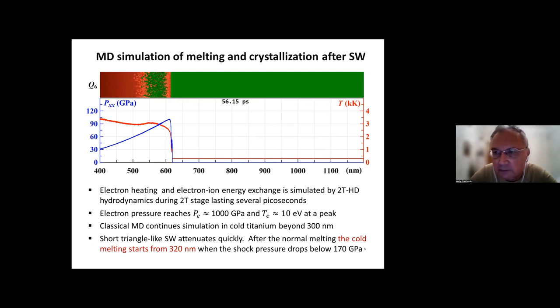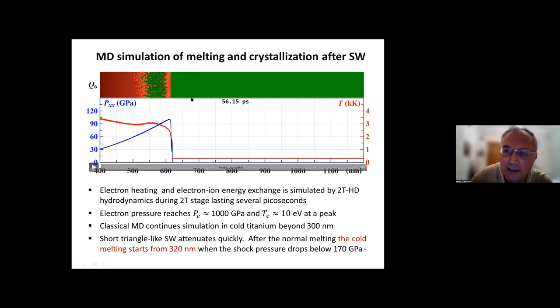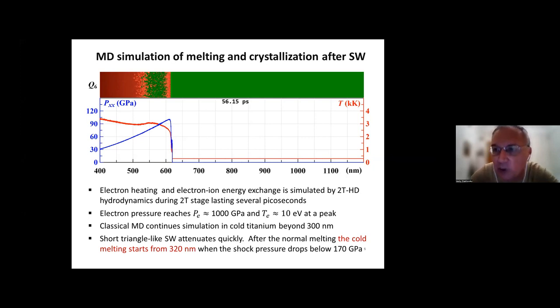Since you mentioned that the shear stress is very important, this actually looks more like Richtmyer-Meshkov instability rather than Rayleigh-Taylor, right? Or it's hard to tell. There is no instability in the hydrodynamic sense. There is instability of the atomic structure of the material due to very high applied shear stress. However, if there is an interface on the path of such a shock wave, it may cause a significant change in the response of this interface. If such cold melting happened around this interface, it may enhance the instability growth rate, and maybe the mixing zone will be larger in comparison with a case where there is no such cold melt.